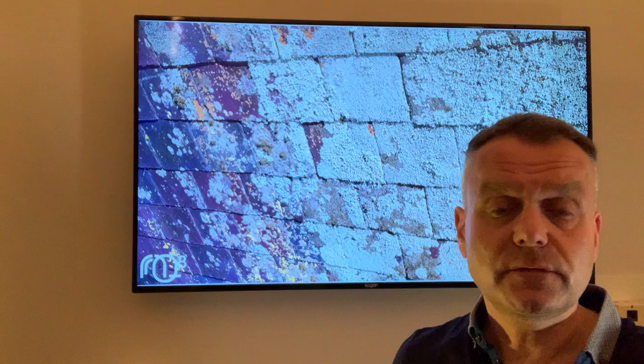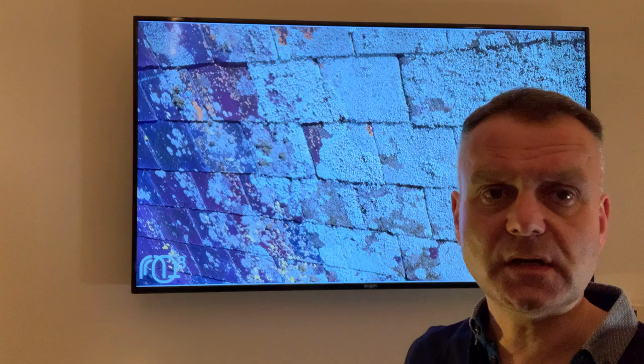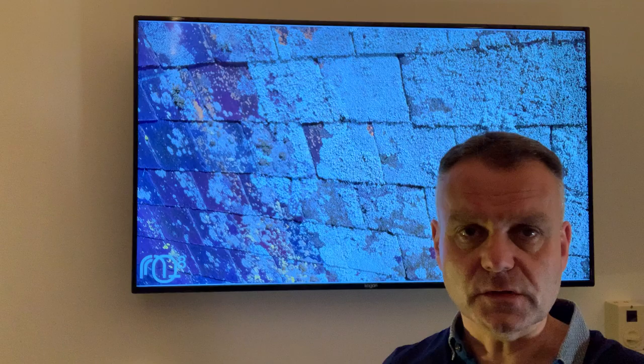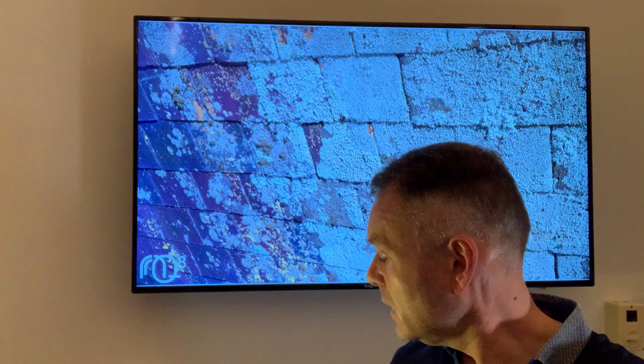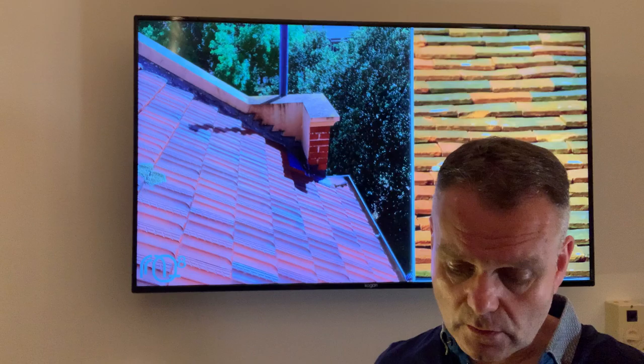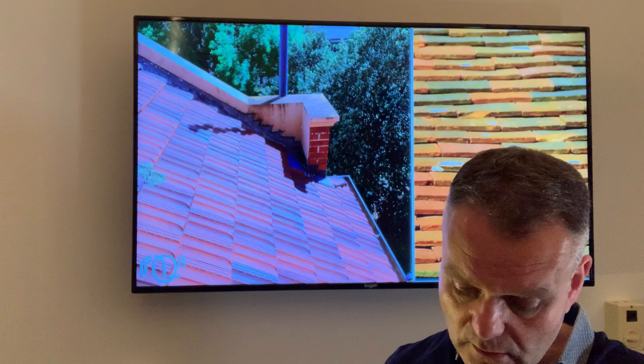This last image about slate shows a very picturesque roof, but the problem is the presence of lichen and mosses. They create a very acidic environment because they secrete digestive juices to absorb minerals and nutrients from the slate, basically destroying its surface and causing rapid deterioration. If you have lichen on your roof, I would strongly recommend getting it cleaned, otherwise you may be replacing your roof sooner than expected.